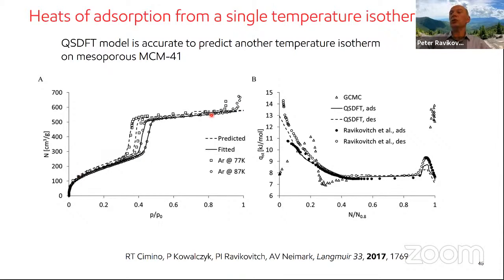Then you can use predictions from the DFT at a different temperature, slightly different temperature, and predict the experimental isotherm at a different temperature. And then you can use Clapeyron-Clausius to calculate the heats of adsorption. And if you do that, it actually gives you really nice agreement with the experiments. Again, this implies that you have a perfect model which is totally predictive from one temperature to the other. This is generally not the case.